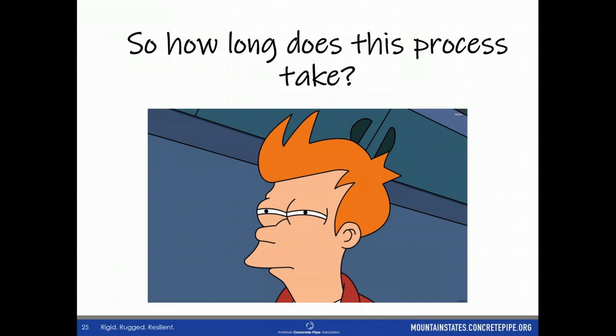Typically, it can happen as early as days or a week, right? It depends on how much water you have. It depends on how big the crack is. That's the other issue, right? When you think about it, if you've got a small crack, say a 1/100th of an inch crack, it takes some time to create those calcium carbonate crystals and fill in that crack. If we're looking at a larger crack, say a 5/100th of an inch crack, that's about the threshold on where this takes hold.